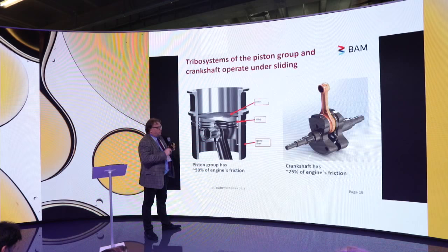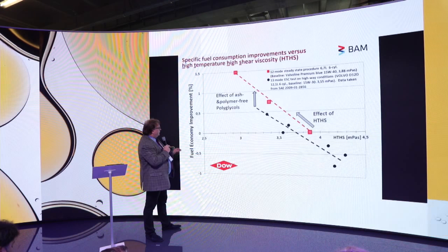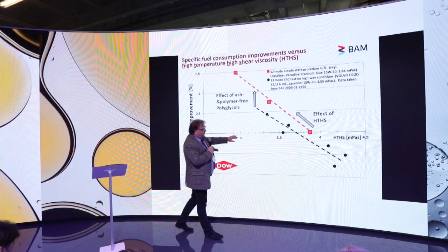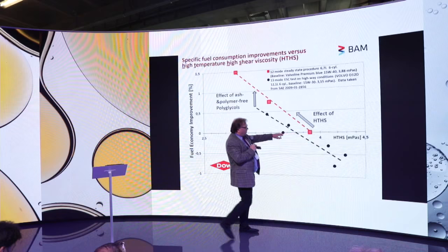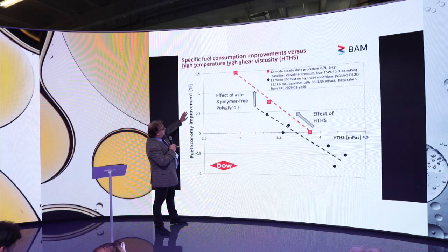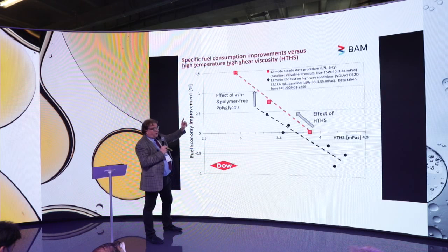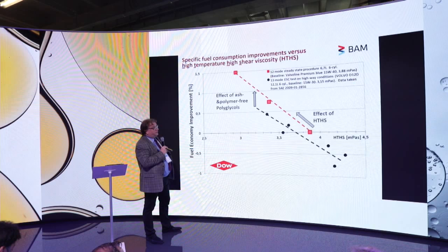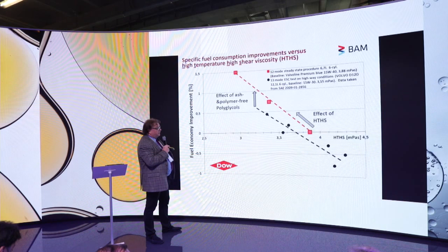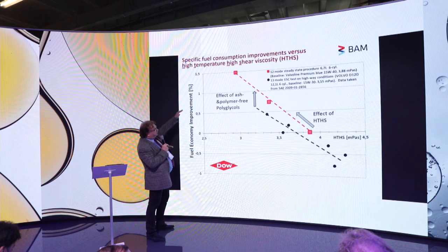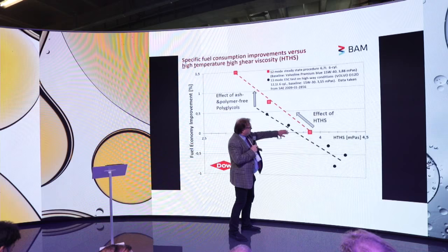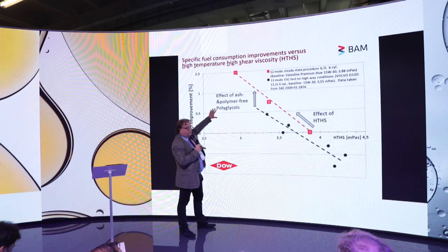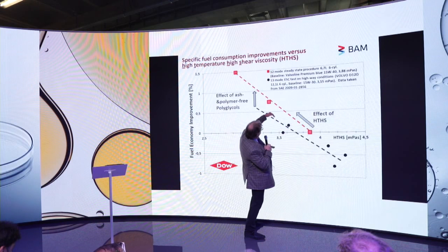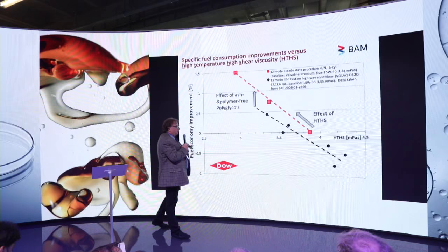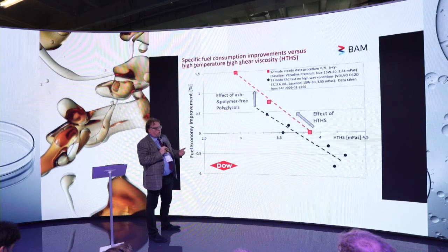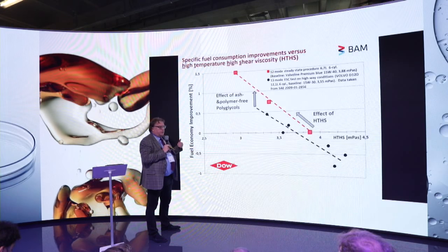And the point is, what happens when you reduce viscosity? Here you have the high temperature, high shear viscosity, and now you go down, and here you see the fuel economy improvement for truck engines, 6.7 liter or 12.1 liter truck diesel engine, and you see you have a fuel economy increase in this line. Now you change to a polyglycol, it's a new chemistry. You have the same trend, but you have a shift coming from the chemistry. So it means having lower viscosity oils reduces friction, increases fuel economy.